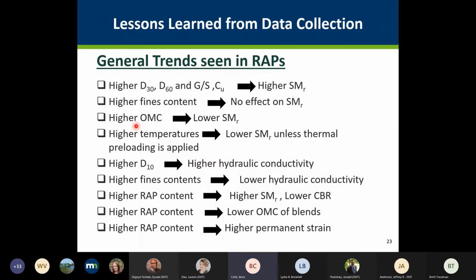And higher D10 value resulted in higher hydraulic conductivity for RAP materials. And higher fines content, as expected, resulted in lower hydraulic conductivity. And again, higher RAP contents resulted in higher resilient modulus value and lower CBR, which were contradicting with each other. And higher RAP content required lower optimum moisture content of the materials, which is expected because asphalt binder is a hydrophobic material, so higher RAP content would result in lower optimum moisture contents in these materials. And as expected, high RAP content increased the permanent strain, the permanent deformation potential of these materials.